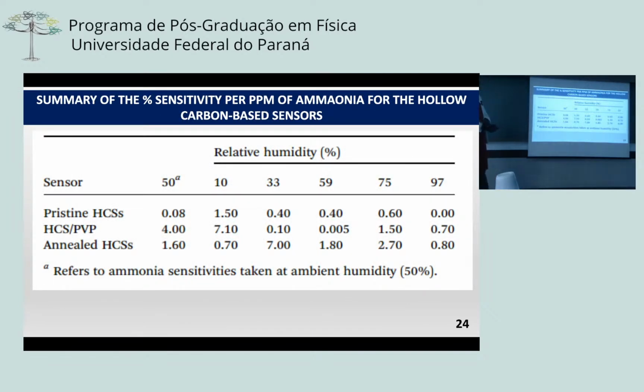And this data here shows the ambient condition. This data here shows the pristine comparison of the sensitivities towards ammonia. And you can see for the pristine above 75%, we're not able to detect ammonia. Why? Because the surface is already oversaturated with the hydroxide ions. And for the polymer at 59% relative humidity, we still obtain very low sensitivity to ammonia. However, for the annealed, it was possible to detect ammonia in all the humidity ranges. That is by just varying the surface groups and their amorphous domains and the structural property, we are able to sense ammonia in a humid environment.